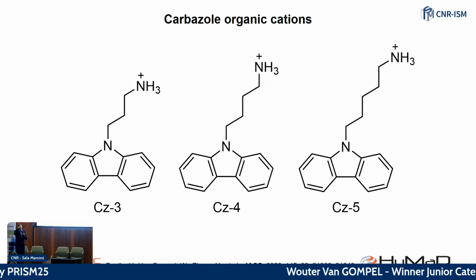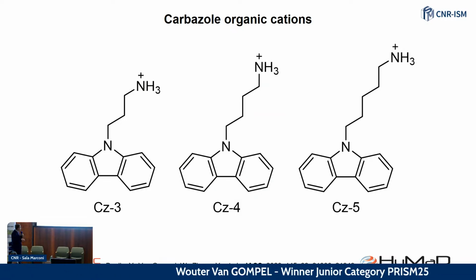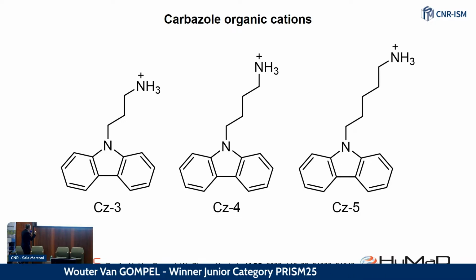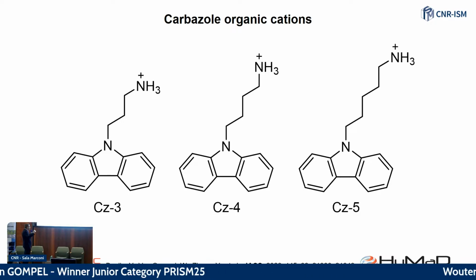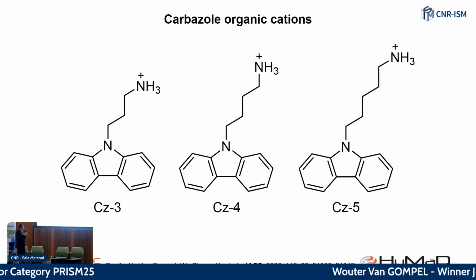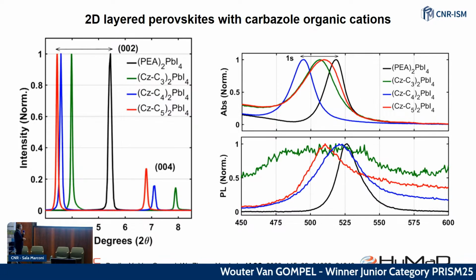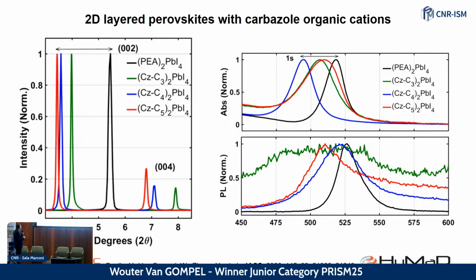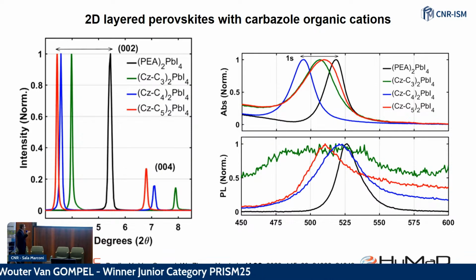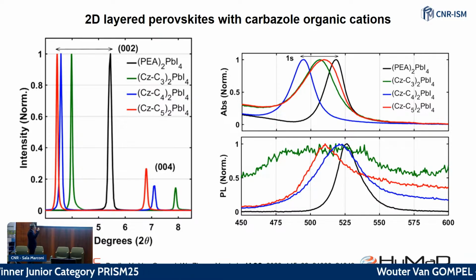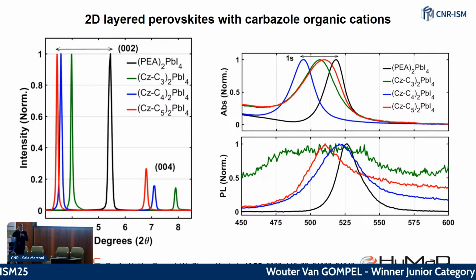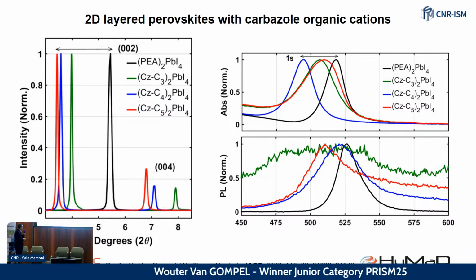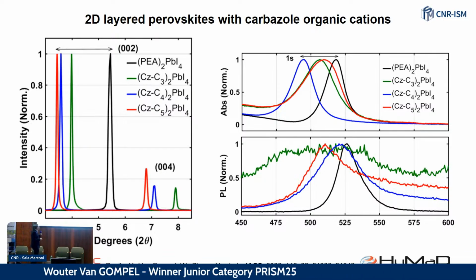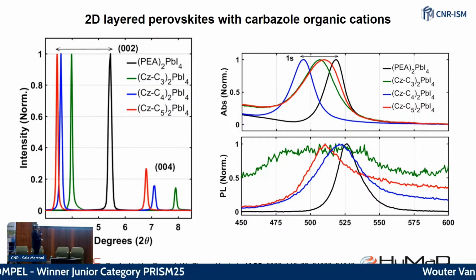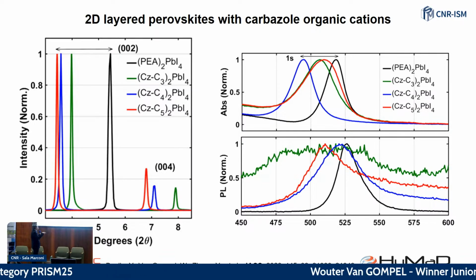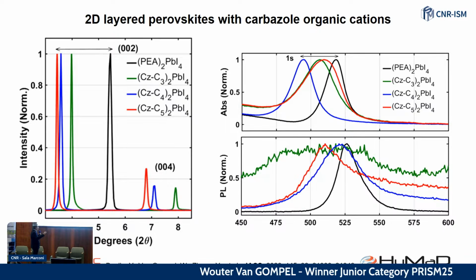What we did is we synthesized different variations of this carbazole molecule with different tail lengths to study the influence of how close the molecule comes to the inorganic framework, and then the rate of the charge transfer process. So some basic characterization: XRD, just to prove that we have the material, and an absorption spectrum with a very typical excitonic absorption peak, because these materials are excitonic. They absorb and they form electron-hole pairs. And the most interesting thing here is the PL, the emission, where you see, normalized, that it's progressively being quenched. The shorter the spacer becomes, the more quenched your photoluminescence.